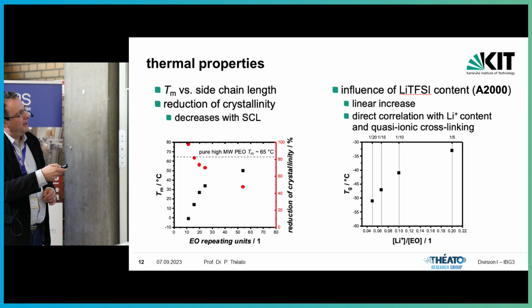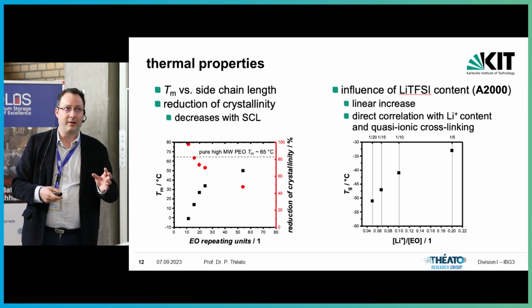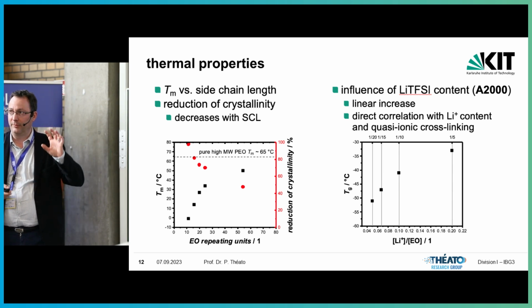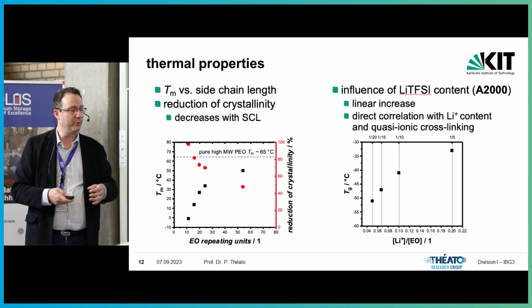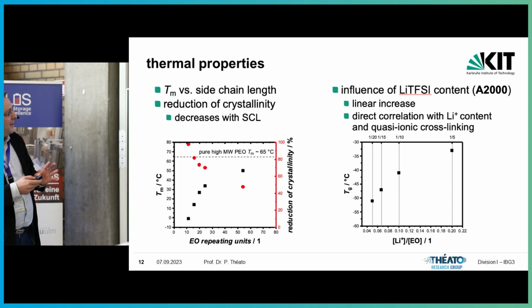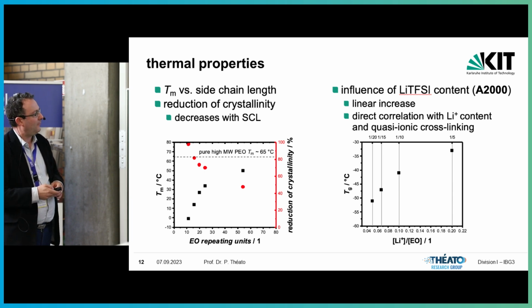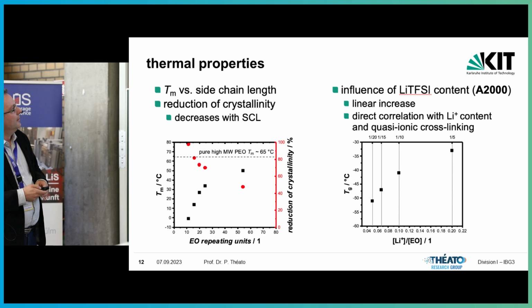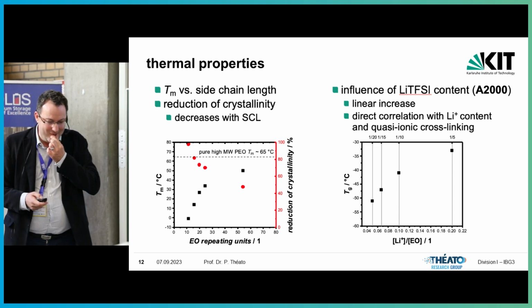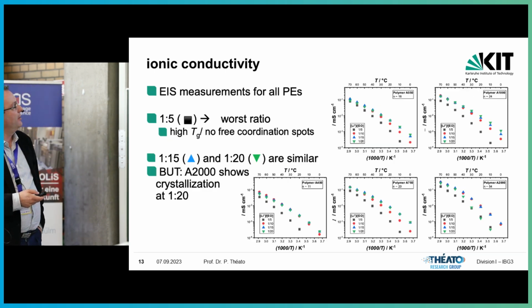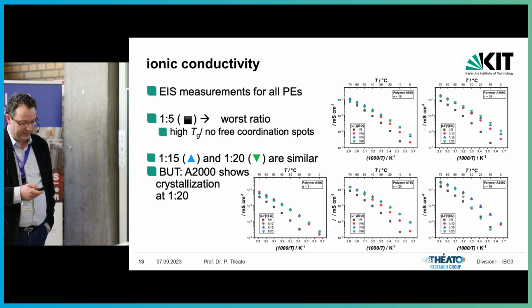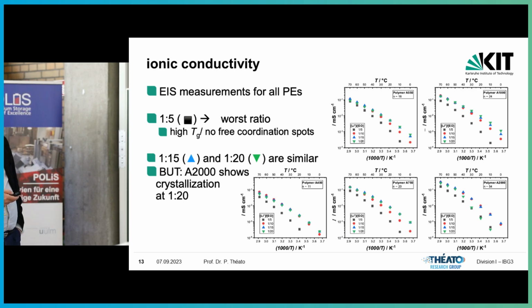And I really highlight this one because the more cross-linking you have, the higher the Tg is, and this is a factor that comes into the game more and more often, because cross-linking density, I think, is something very important to control. So this is something to really have a look at. So this is nice. How do the conductivity data behave? So we screened different lithium to ethylene oxide ratios, which you can see here.